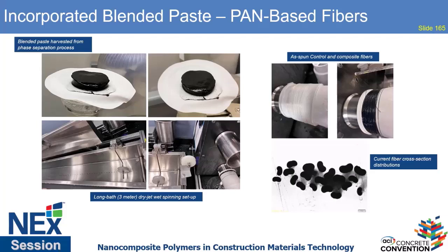So you have to then remove all of that non-solvent to then make it into the dope that's going to spin a fiber. You then also have to bring the viscosity of that dope up to the right stage so you have filament stability in order to make sure you can make a good fiber. So it's not trivial, but we were able to do it, and this is a little bit of a snapshot of part of our system.